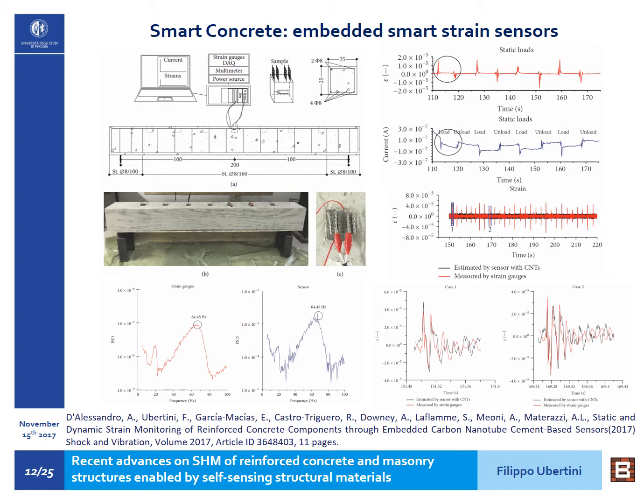Then you also see the results of a test with hitting the beam with a hammer in random locations over the beam. You see in red the measurement of a strain gauge, and you see in black the measurement of a smart concrete sensor at the same location of the strain gauge. If we take a detailed view of a single hit, you clearly see that the time series of the measured strain is very well superimposed to the time series of the electrical output of the cement-based sensor.